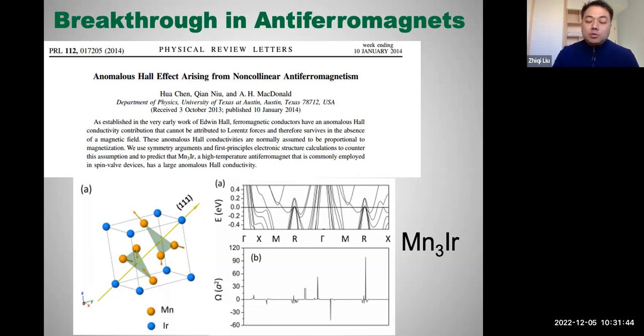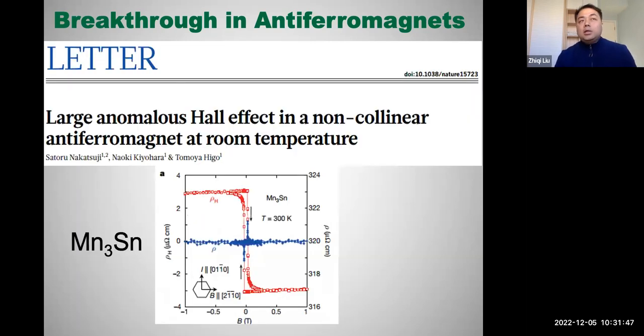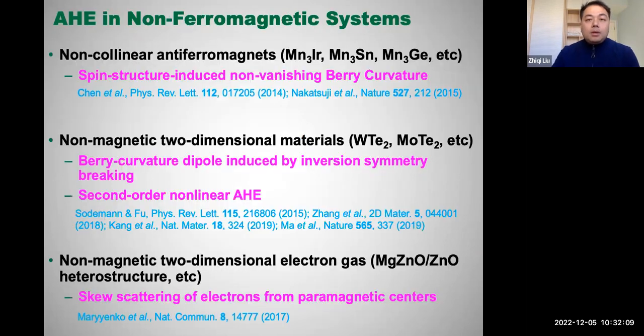They made this theoretical prediction in 2014, and quickly, less than one year after the theoretical prediction, Prof. Nakatsuji's group at Tokyo University experimentally observed a very large room temperature anomalous Hall effect for the antiferromagnetic metal manganese tin. This could be another important breakthrough for antiferromagnetic spintronics. If we now look at the anomalous Hall effect in non-ferromagnetic systems, we have non-collinear antiferromagnets, we have non-magnetic two-dimensional materials, we can also have non-magnetic two-dimensional electron gases.